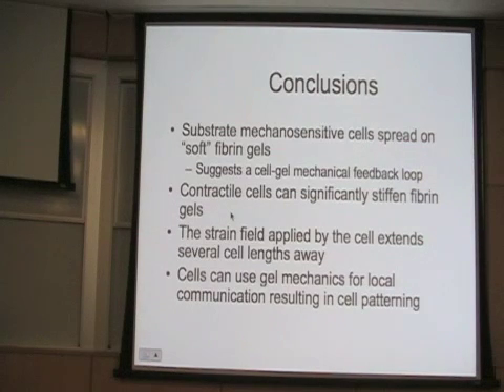Okay, so let me finish there by concluding that in a very cell type specific way, cells respond to mechanical properties of their substrate, but they respond differently, presumably because they have different levels of force that they apply to materials, but also they have different signaling pathways. So it's very difficult to predict what one cell will do and another cell might not. But the contractile cells, the ones that are the most efficient at yanking on the materials, one of the things that they do to the natural materials is locally stiffen it. And that local stiffening, as well as the tension that they apply, is one of the stimuli to which their neighbors respond, and this mechanical thing is a way for cells to respond to cues that are hundreds of microns away, much farther away than could be accomplished by touching.